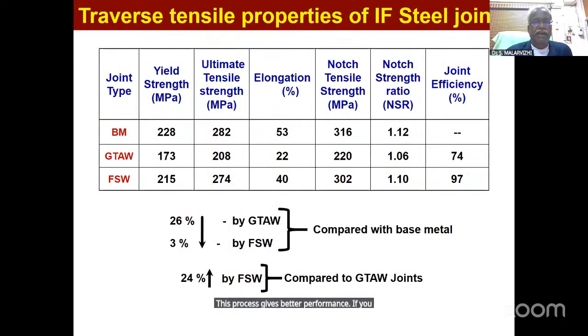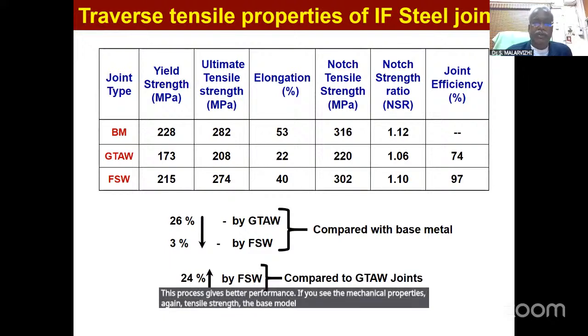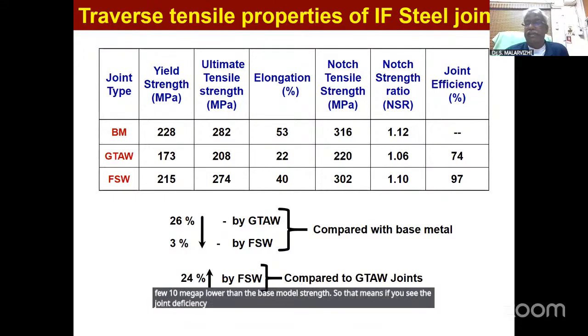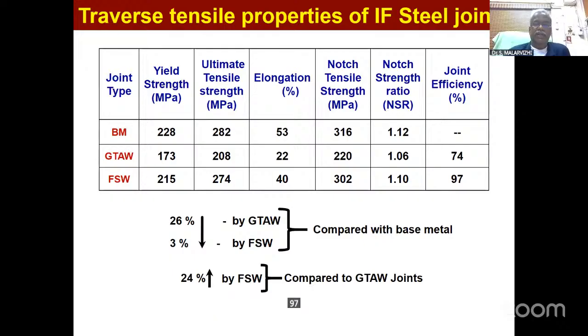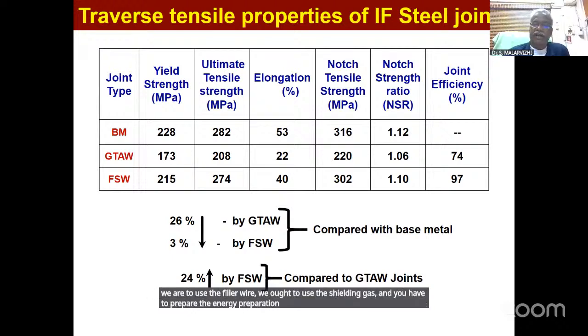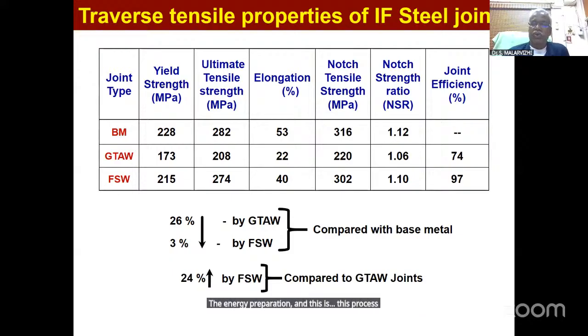If you see the mechanical properties, the base metal tensile strength is 282 megapascal, but TIG welded joints yielded only 208 megapascal, whereas friction stir joints yielded 274 megapascal, just a few 10 megapascal lower than the base metal strength. So the joint efficiency is 74% in TIG welding, and 97% we have achieved in FSW. But in TIG welding, the problem is we have to use filler wire, shielding gas, and edge preparation. Here there is no shielding gas, no need of filler wire, no need of edge preparation, and this process has no smoke, no fumes, no radiation. That's why this process is known as the green welding process or clean welding process.